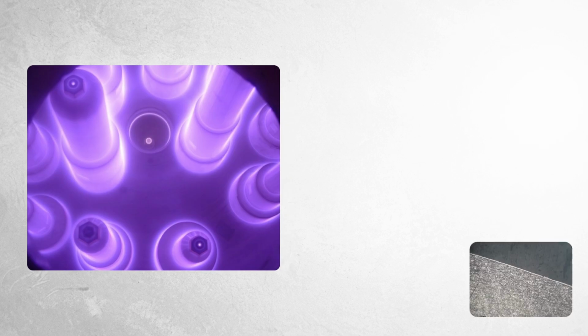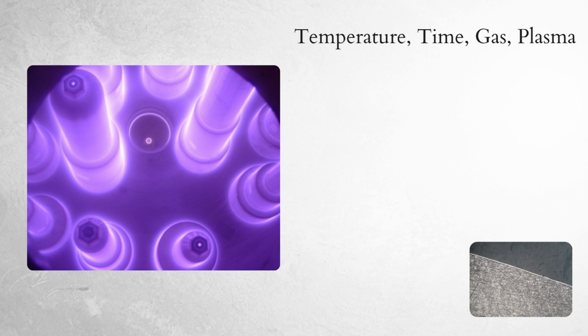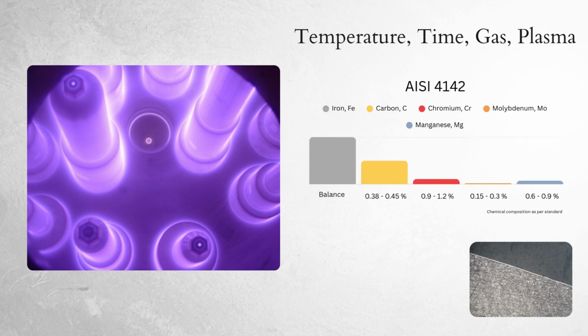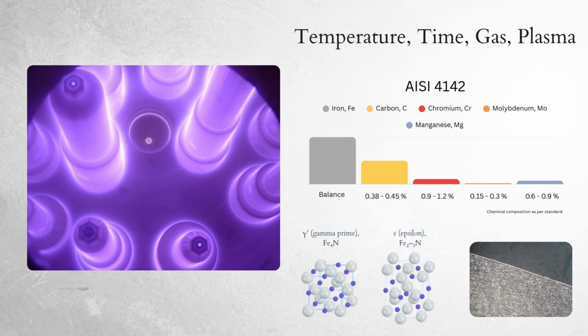One of the main advantages of ion nitriding is that the formation of the white layer can be controlled with relatively high precision. By adjusting the process parameters and considering the steel grade, it is possible to obtain a high-quality compound layer that is predominantly gamma prime, predominantly epsilon, a mixture of both, or minimal or no compound layer at all, depending on the part